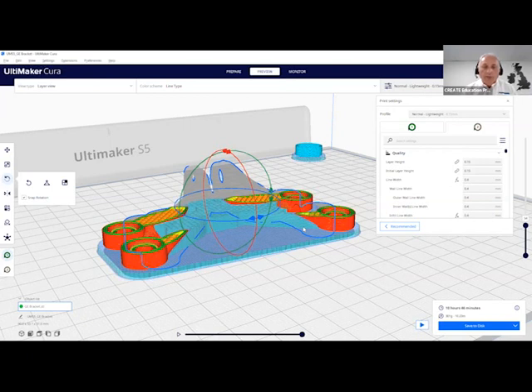So you've got a friction effect between the base of the part, which is shrinking and contracting, and the shelf that it's sat on, which is not contracting at all. And that friction, depending on the geometry, can result in some distortion of the part geometry. By printing on top of this shrinkage plate, you transfer that drag to the underside of the plate where it doesn't actually matter. So in this case, where that plate is down onto the glass build plate, that's now where all of the drag is happening.